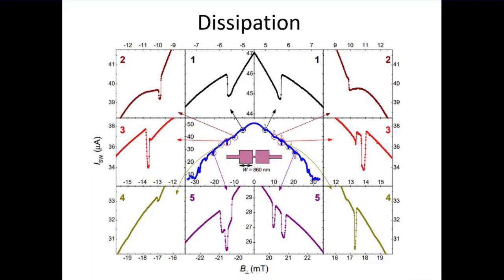the second vortex, which is captured here, is expelled during readout. So when we try to measure the critical current, we measure with pulses, yes? Before we come to the point when this bridge switches, first the vortex is expelled from the box, and when it's expelled, it creates dissipation, it creates quasi-particles. So this box is heated. When it's heated, the critical current changes. It's very sensitive to temperature. And this kind of suppression is a result of dissipation appearing when we push a vortex out of the box.